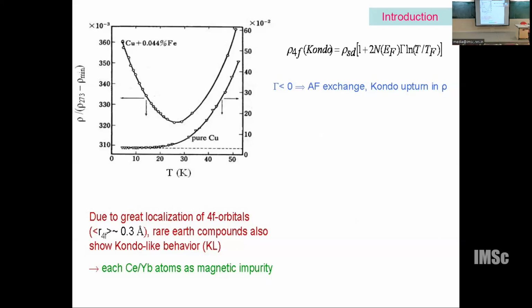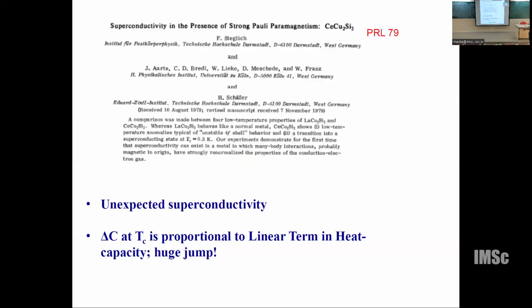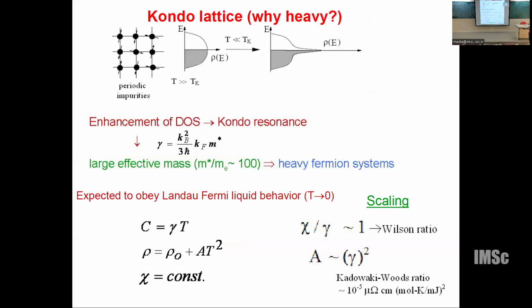Okay, now how does it come about? Since you asked me, when it comes to rare earths, as I told you, 4f electrons are not as delocalized as the d. There is some degree of localization. At low temperature, they get delocalized. Therefore, they have a tendency to form a singlet ground state at every site. If we talk about cerium metal or any other cerium aluminum 3 or any compound, they form a high temperature free electron local moment, and at low temperature they form a ground state. Therefore, at every site, you can form that so-called Kondo singlet state. They call these Kondo lattices. There is a periodicity of the singlet ground state in the lattice. It's called Kondo lattices.